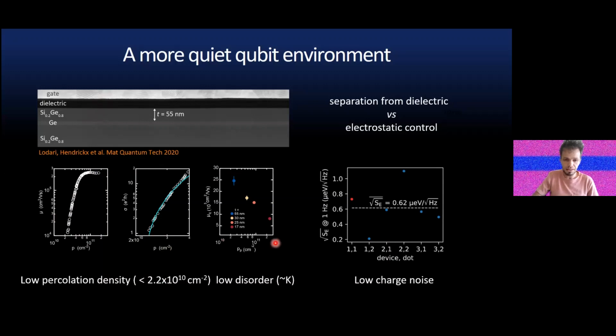Another thing that we highlight in this paper that I want to bring to your attention is this. If you look a bit beyond the simple qualitative metric of mobility, which captures only scattering that is relevant for transport, and look at quantum mobility, which captures the lifetime, the tau q, the single particle lifetime, this takes into account all scattering events at all angles. This is probably a better metric to qualify your material if you're thinking about spin qubits, because it captures every possible nasty thing in the crystal environment that could influence your performance.